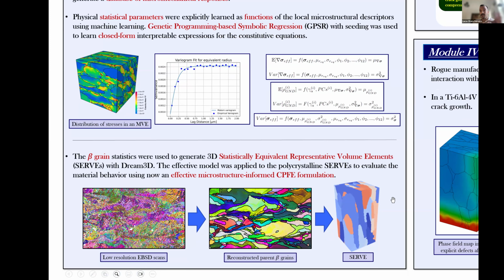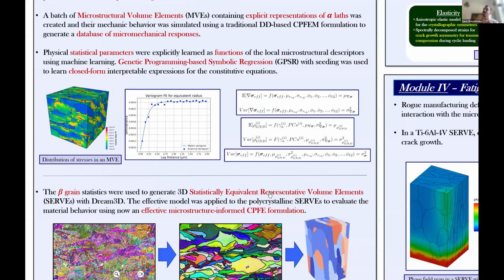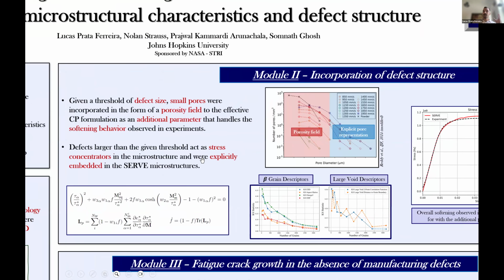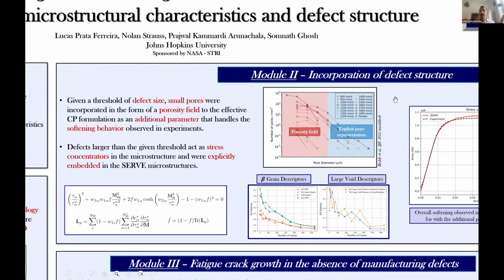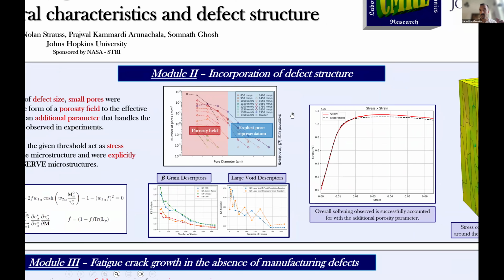But great, that gives us information on the microstructure, but we also need to take into account the defects. Due to the manufacturing process, we can have a very broad range of defect sizes and shapes. So we decided to embed these defects in our modeling in two different ways. For very tiny defects, we consider them as a porosity field that is described in the whole domain, and we add an additional parameter f in the crystal plasticity formulation in the Gurson type model, such that we can account for the softening behavior that is expected from and observed in experiments.